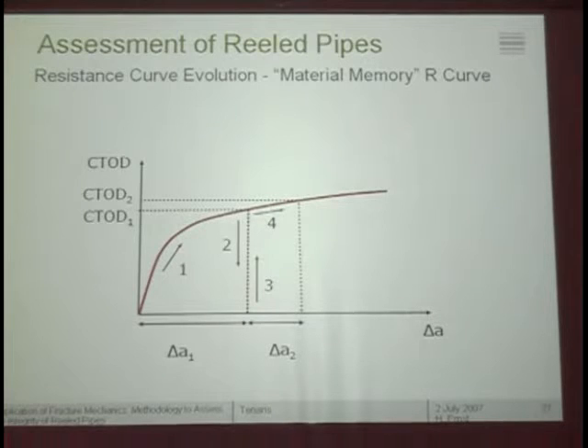Whereas the material memory resistance curve is somehow like plasticity, more or less, in the sense that you have to get to the same value that you were before you can extend the envelope. So that means that you go to some CTOD, you have the same crack extension as before, but when you unload and you go to a second CTOD, the extension you have is only this much. This is the same as saying that if you have a second cycle in which the CTOD is bigger than the first one, you can sort of forget the first cycle completely, and you will have the total crack extension given by the maximum CTOD of the two.